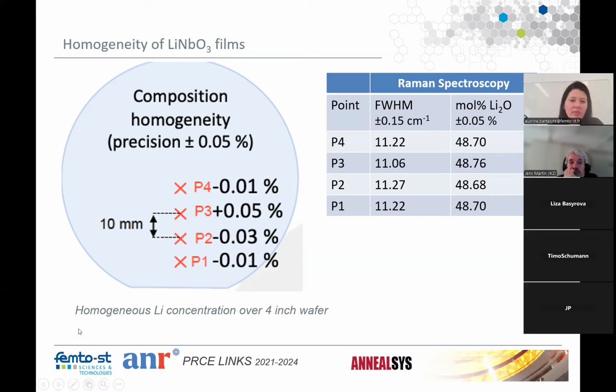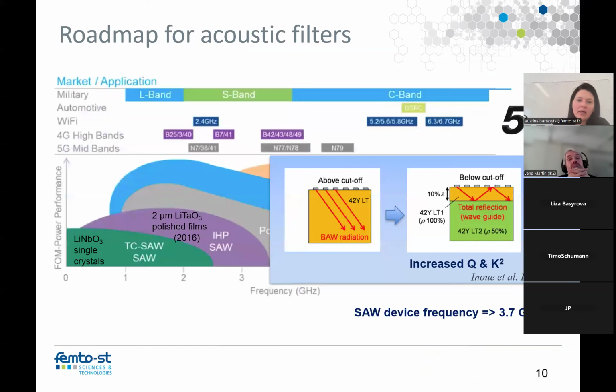Here you see we measured by Raman at different points. We had many more points; I just put four here to show where we are within the errors. Basically, this is my precision, so I put the absolute precision for single crystals. We saw that it varies in absolute value by a very, very small amount, basically within the errors. So it shows that the composition across the wafer is homogeneous.